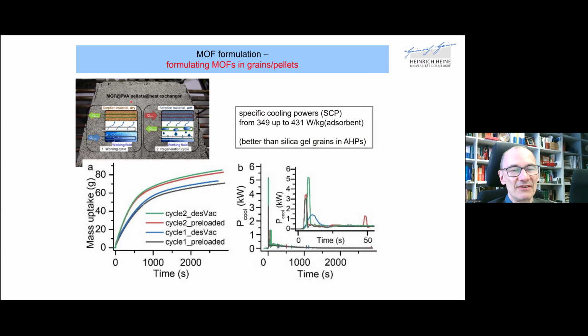We also tried other polymers, of course. Some others also worked, but some didn't. And what was also important is that the polymer does not block the pores of the MOF. So we had proven through separate investigations that the porosity of the MOF was to a large extent still accessible for the water. It would be no good to have a polymer which really covers or coats the MOF such that the porosity is no longer accessible. And so in that aspect, polyvinyl alcohol was doing well.